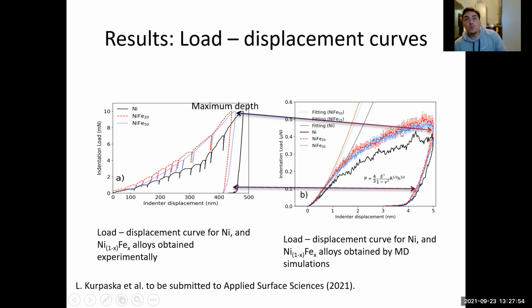And in the MD simulations, since we have the constant rate for the indenter tip, we know where we are going to end up. This is the maximum depth. So when they end up at the maximum depth at the given initial load of the tip, for nickel you can see that you can go deeper in the material. And then when you have nickel iron with 20% of iron, under the same parameters, the tip doesn't reach the maximum depth in the sample. And when you have 50%, it also didn't.